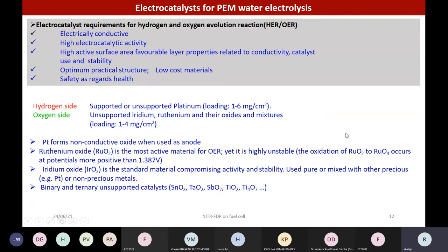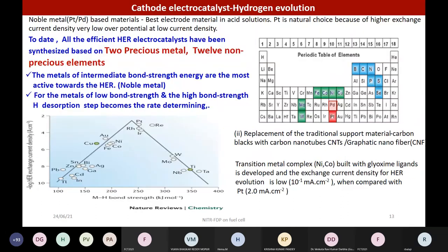So that is the reason people are using an unsupported electrocatalyst for the oxygen evolution reaction and a supported catalyst for the hydrogen evolution reaction, because the hydrogen evolution will take place at 0 volt. In that case, there may not be a possibility for carbon corrosion. So in that way, you can use a carbon supported electrocatalyst for the cathode side and an unsupported catalyst for the anode side.